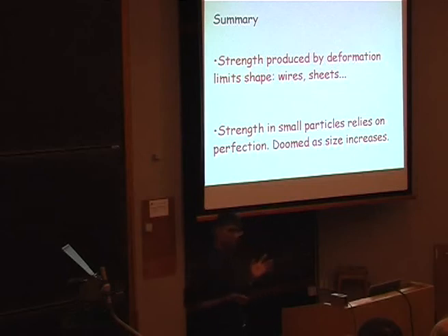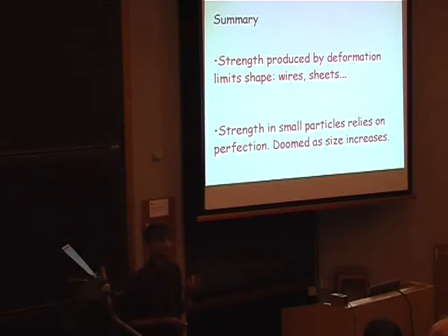And of course, what they've forgotten is that when you rely on strength from perfection, that will always fail when you scale the system up. So we cannot really do that. Strength in small particles relies on perfection and is doomed as the size increases. Thermodynamics tells you that even in principle, you can't scale it up. And the strength produced by deformation limits the shape.